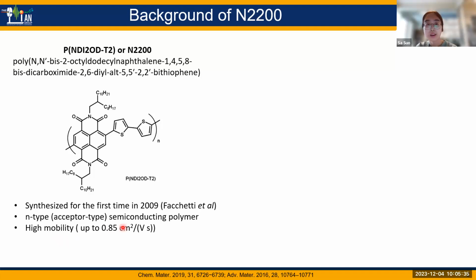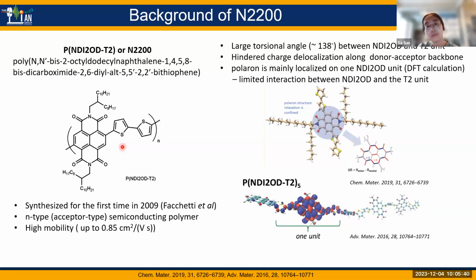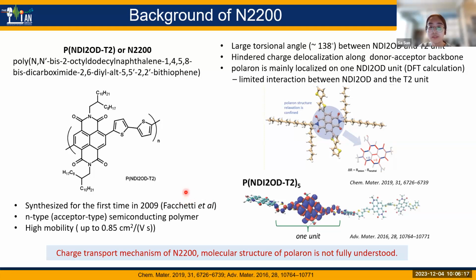However, the previous DFT calculation indicates that there is a large torsional angle between the NDI2OD unit and T2 unit, which partially hinders the charge delocalization along this donor acceptor backbone. And as a result, they predicted that the polaron is mainly localized on the NDI-2OD unit with limited interaction between the T2 and NDI-2OD unit because of the large torsional angle. So far, this is the current understanding of the polaron confinement in this polymer, and I believe the charge transport mechanism of N2200 and also the molecular structure of the polaron has not been fully understood. So we should dig more into that.